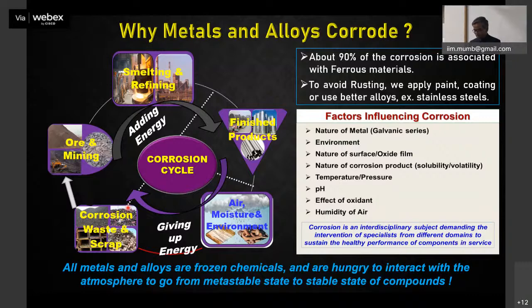There are a number of things that matter, particularly the status of the metal. We have a galvanic series, from the active end to the noble end, so where the metal sits is very important. Then the nature of the environment, the nature of the interface that forms between the metal and the surface. Then we have the knowledge about the product that is forming, maybe some oxide, some product which is porous or continuous. Then environmental parameters like temperature, pressure, pH, and oxidizing or reducing ions present. Even in air, the relative humidity is very important.